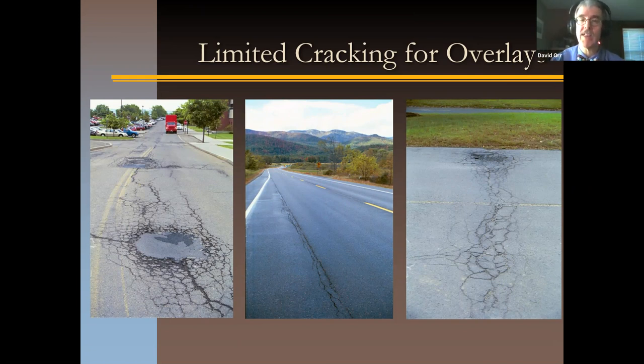And as a good rule of thumb, a nice solid crack is going to come through about 1 inch of asphalt in about a year. So if you've got 3 or 4 inches of asphalt, you're only going to get 3 or 4 years before those cracks start to reappear.